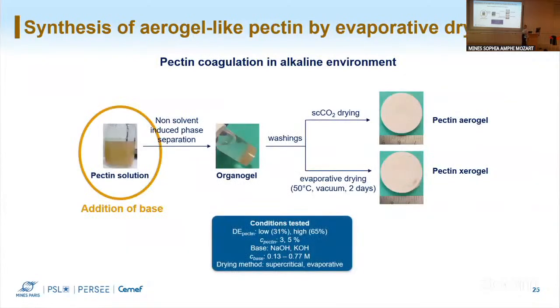When we make pectin gels in acidic conditions, we do coagulation in the non-solvent, so we only get the structure because of the solubility change of our pectin chain. When we use a high concentration of base, we already get a coagulated network without adding a non-solvent. So in these conditions, pectin is not soluble anymore.